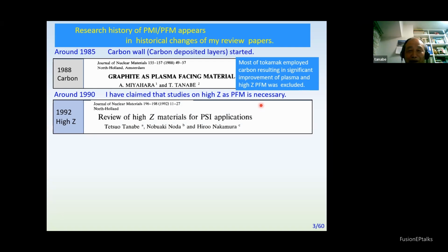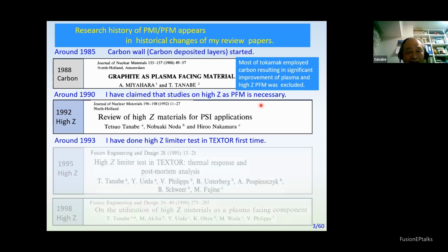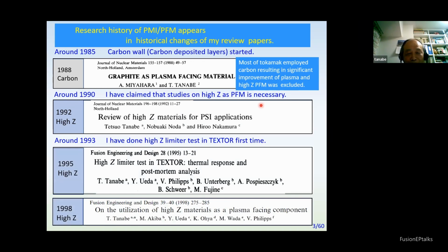And then most of the tokamaks changed to carbon machines, but I was afraid that too concentrated a use of carbon is dangerous, so I claimed that studies on high Z as PFM are necessary. And then I did high Z limiter tests in TEXTOR, because no one wanted to use high Z materials on plasma facing surfaces. So I tried to convince people to do such an experiment in TEXTOR, and I succeeded. Since then, together with colleagues of the TEXTOR people, I have made a lot of experiments on high Z materials as plasma facing materials.